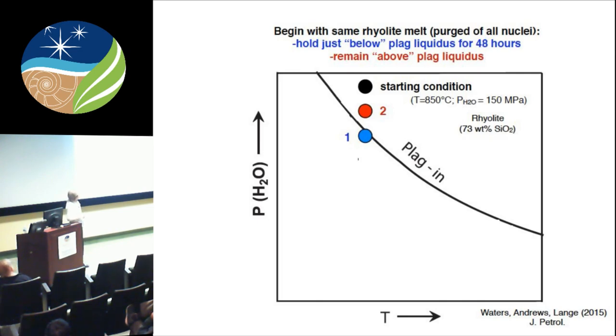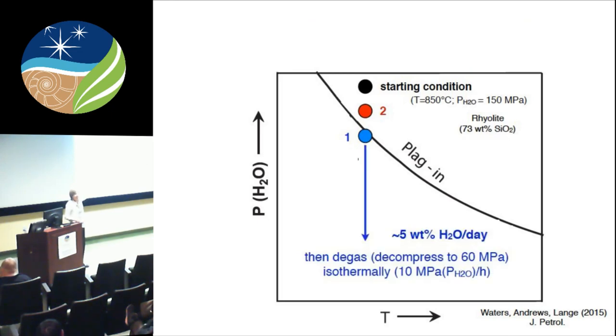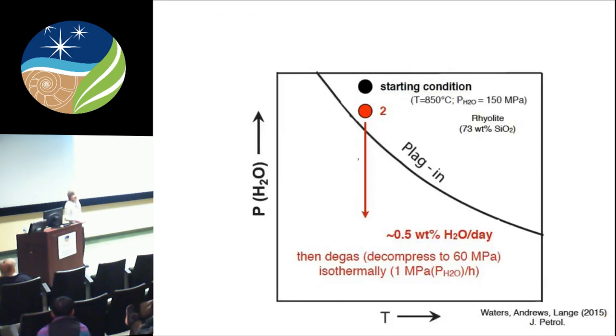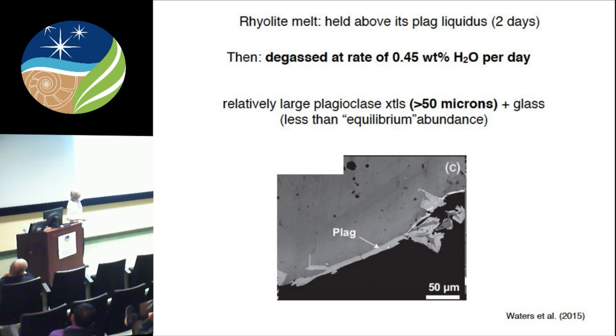If you then take that sample, redo the experiment, and decompress it at a rate of around 5 weight percent water a day, so that's maybe 5 or 6 hours, and then quench it, this is what you get. You get lots of crystals, tiny crystals. You do the same thing with the one that's just a little bit above the plag-in curve. This time, it's an order of magnitude slower, so more like 55 hours instead of 5.5. You get glass. You do it just a little bit slower, at 0.45, and you get a fairly large crystal, 50 microns. So it doesn't look exactly like some of the microphenocrysts in the sample, but the general trend is there.